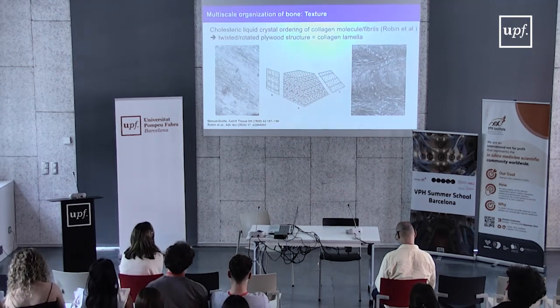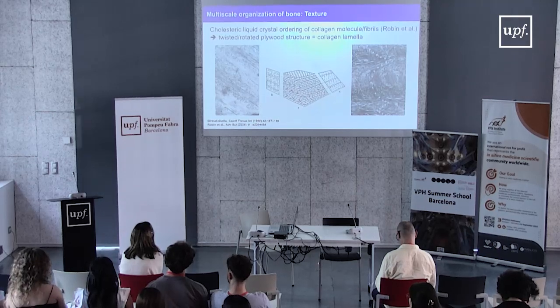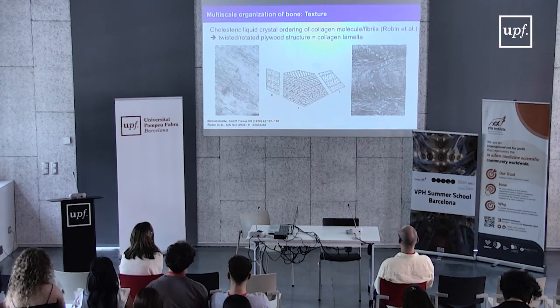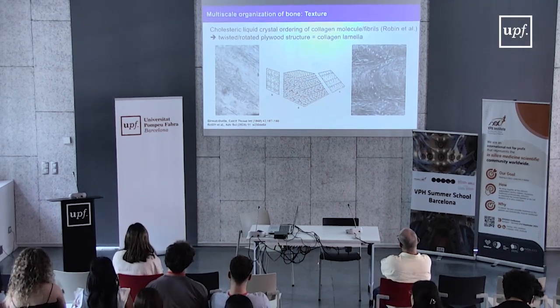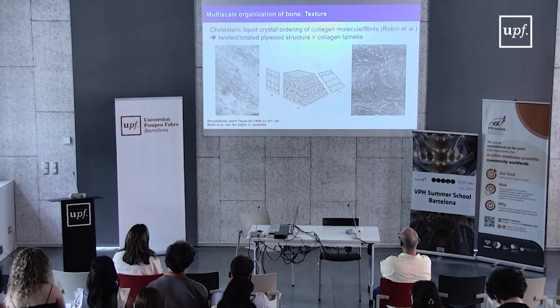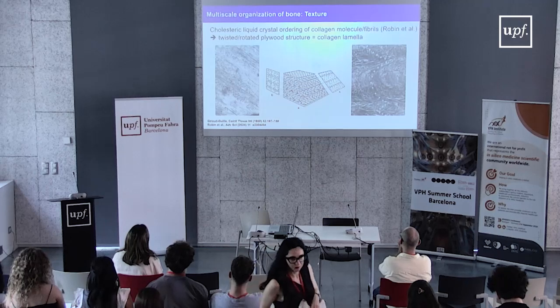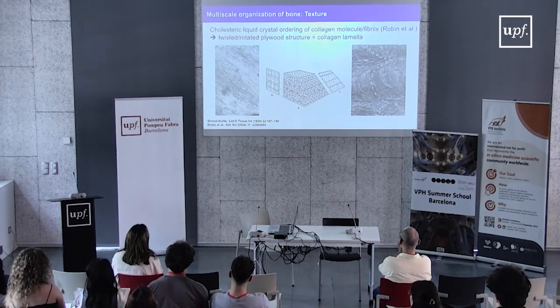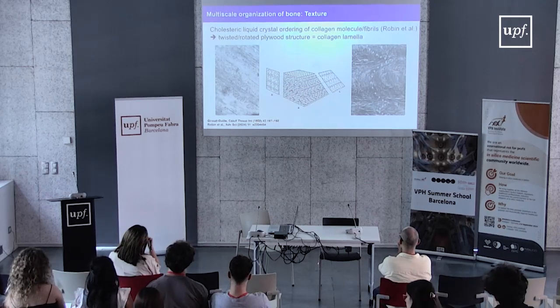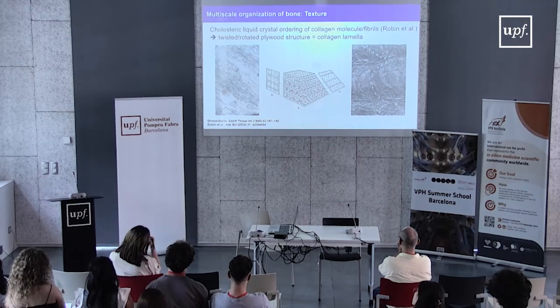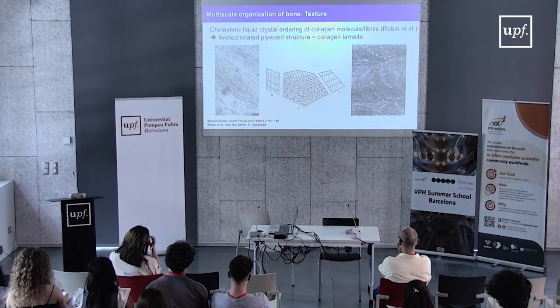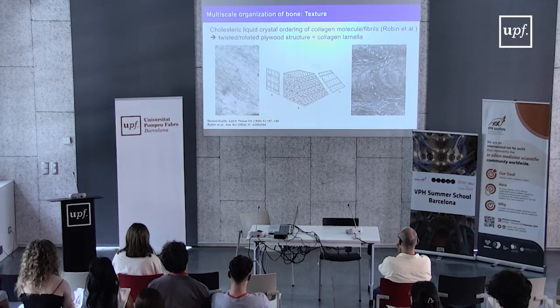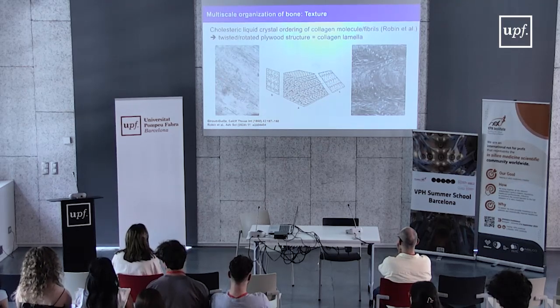The collagen fibers are deposited like a liquid crystal in the shape of a cholesteric form, and it will make the collagen fibers slightly orientated to each other. If we look by electron microscopy in 2 different axes, here you have the structure and the model for the cholesteric liquid crystal of collagen fibers. If we cut the section alongside this plane, we will see theoretically this pattern of fibers. And indeed, when you do TEM and the collagen is cut in this pattern, you can see different alignment. You have here collagen fibers which are cut longitudinally, and here collagen fibers that are cut cross-sectionally.